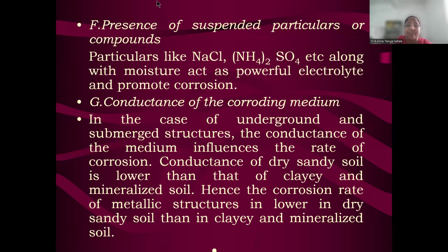Then the other factor is conductance of the corroding medium. In the case of underground and submerged structures, the conductance of the medium influences the rate of corrosion. Dry sandy soil has lower conductance, so the rate of corrosion will be less. Whereas in a liquid medium, the conductance would be greater, so hence we could see high corrosion tendencies. So these are the different factors that can influence the rate of corrosion.